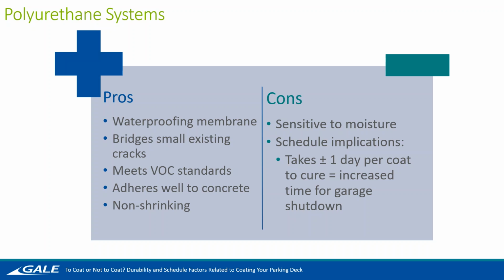Some of the cons: it's sensitive to moisture. As I said, it cures relative to the moisture in the air and whatnot. It was a little bit better than that 1-part system, but it still takes a little bit longer for it to cure. And then schedule implications. It takes roughly 1 day for each coat to cure. So that increases the time your garage is shut down.